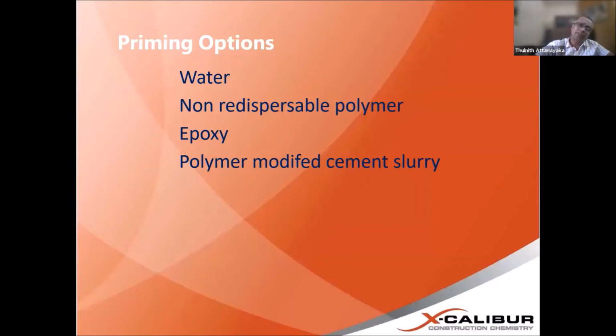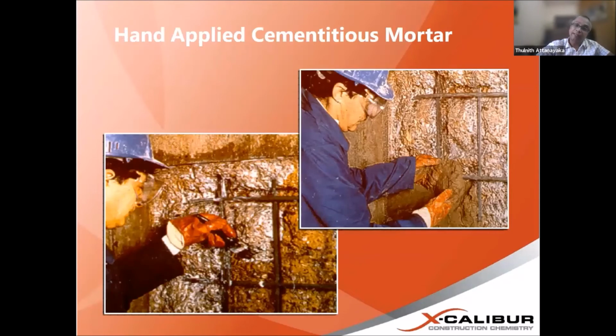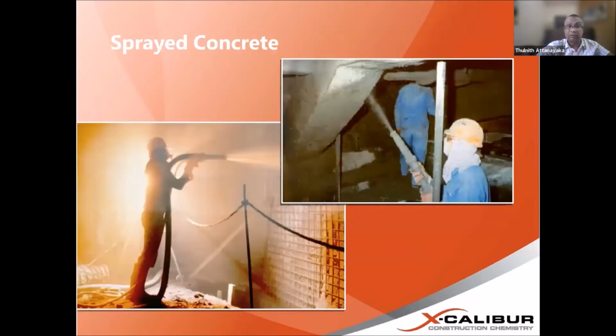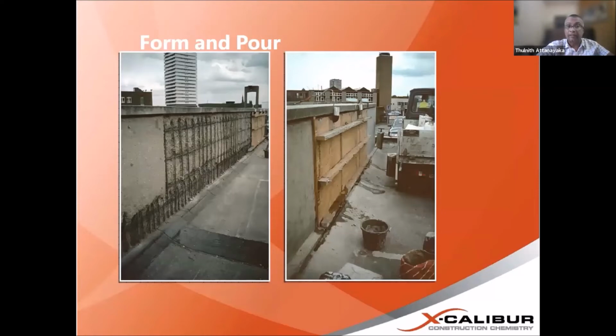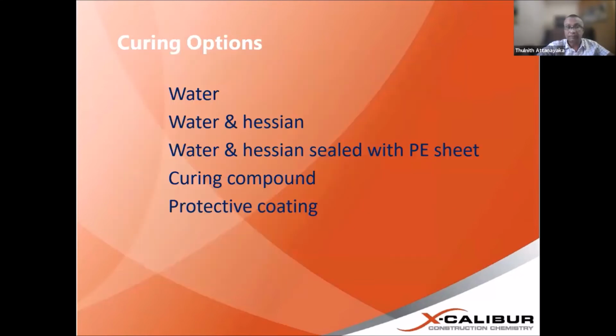When it comes to priming options for the repairs, we can use water, non-redispersible polymers, epoxies, polymer modified cement slurries. And we can use hand applied mortars for small areas, sprayed concrete like shotcrete for big areas, form and pour if you have self-compacting concrete or micro concrete, using formwork. When it comes to curing options, again, you can use water and hessian, polythene sheets, curing compounds, and of course protective coatings.